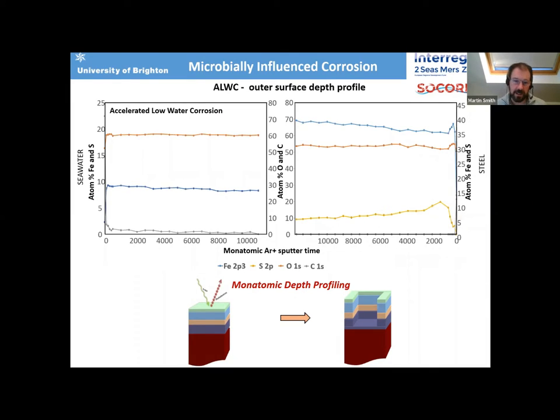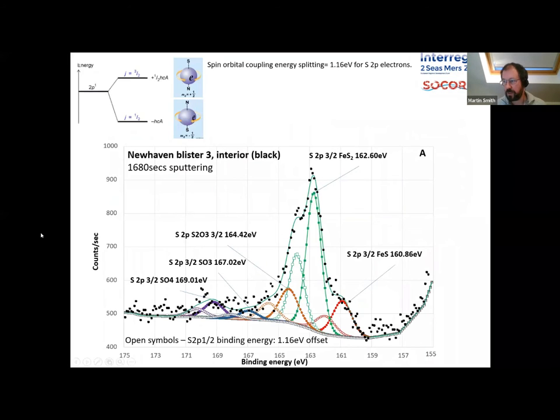When we look at an accelerated low water corrosion sample, we see the same thing, but higher sulfur concentrations. So we're going up to 15% sulfur towards the steel surface as we profile into these materials. So for each of these points, we can then abstract a binding energy spectra and look at the actual chemical state of the elements we've analysed there.